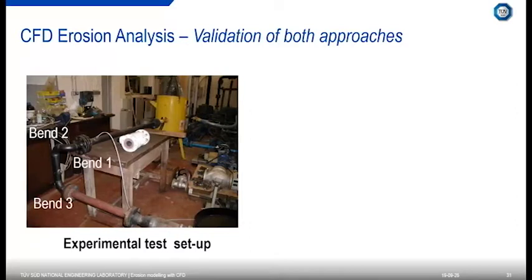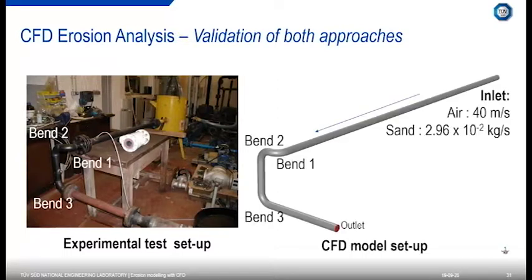So one other point that I did mention before was that you need to be confident in your erosion modeling. Here I have an experimental test, and this was done in 2-inch pipework, and it has 3 bends. This was done a number of years ago. On the left-hand side is a picture of the setup. We have gas and sand coming in, impacting bend 1, bend 2, and bend 3. So we've taken some measurements, and we can then set up our CFD model. We have our inlet, outlet, and our three bends, and that's the flow direction.